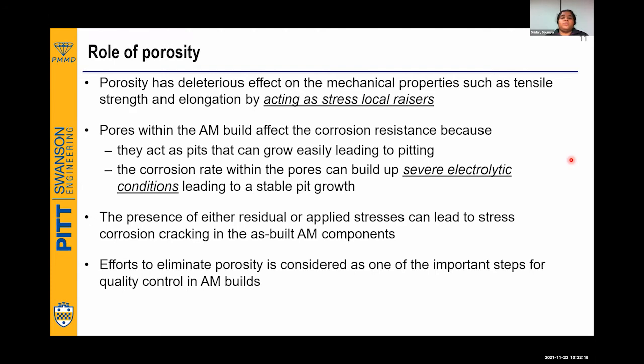So the corrosion rate within the pits will build up because of severe electrolytic conditions, leading to stable pit growth. And a small pit which goes throughout the sample is going to lead to cracking further. And the presence of residual or applied stresses can also lead to stress corrosion cracking. Hence all these three problems are not simple, and they have to be dealt with. So eliminating porosity is one of the important steps for quality control of AM.